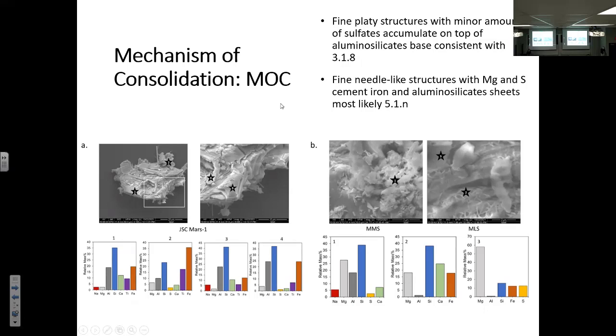So the lunar samples are dominated by the 5.1.n phases. These phases form needle-like structures. So you're talking about a higher surface area. The needles are better and well incorporated in the consolidated sample compared to a platy sheet. And so they do a much better job of just reducing the overall porosity of your sample once it's cured.